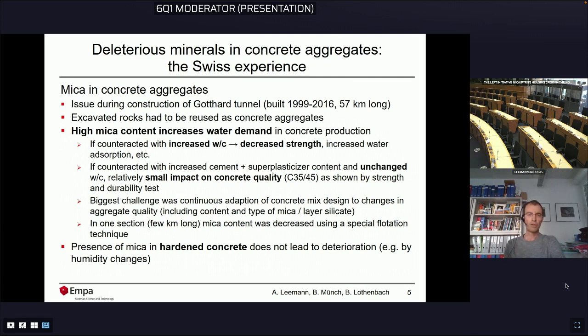The biggest challenge during the project was the continuous adaptation of concrete mix design to changes in aggregate quality, and this included content and type of mica and layer silicates. So we had all types of mica and layer silicates possible, more or less. Just no clays, I have to mention this. In one section that was a few kilometers long, mica content was decreased using a special flotation technique. And what our experience has clearly shown: presence of mica in hardened concrete does not lead to deterioration like by humidity changes. The mica we have in Switzerland show no swelling at all. Okay. Now, please to the next slide.